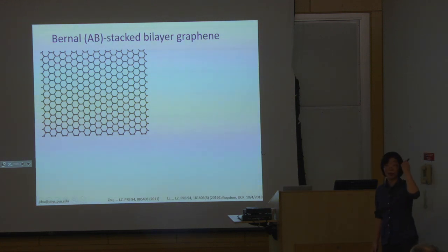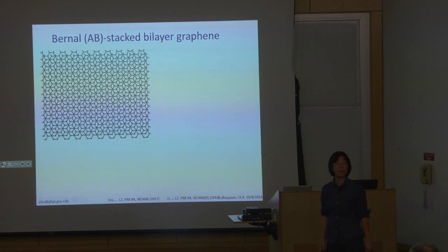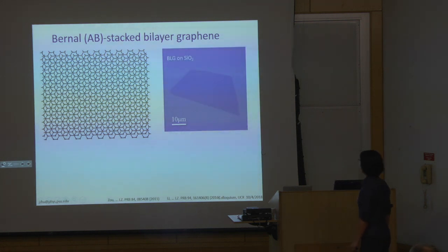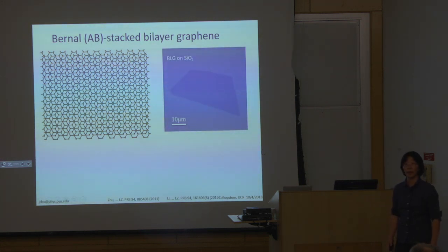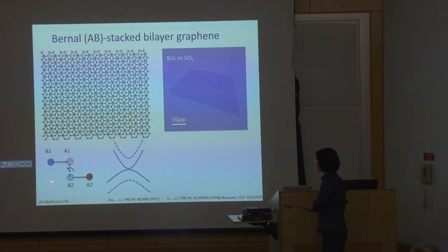And that something else is to add another layer to it. So bilayer graphene stacked together in this fashion, AB stacked. Okay. That's how they look when we take them out of HOPG graphite and put it on an SiO2. A lot of people here work on two-dimensional materials. If I look at the side view of this stacking over here, these two guys interact strongly because they're stacked on top of each other, and they form these dashed bands that are away from the Fermi level.